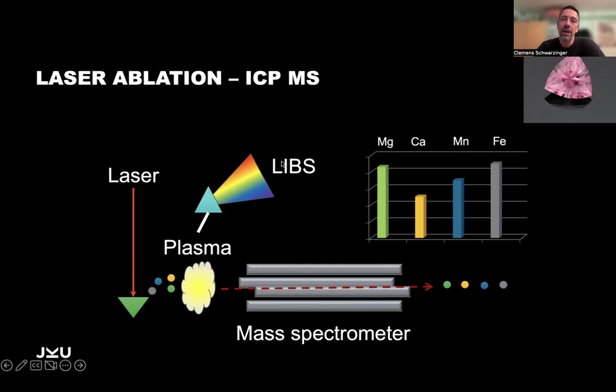So the question now remains, if LIBS is cheaper than ICP-MS, why doesn't everybody use LIBS? Because LIBS has one problem, the limit of detection is not as good as in the laser ablation ICP-MS. In the laser ablation ICP-MS, we're talking about ppt detection limits. I mean, you know, ppm is parts per million, ppb parts per billion, ppt is parts per trillion. So you really detect the smallest amounts possible in your structures. And with the LIBS, you're in the higher ppm range. And sometimes 10 ppm can be not enough. They already induce the color, but if you don't measure them, you may lose some information. So therefore, the LIBS is nice, but not as nice as the laser ablation ICP-MS.